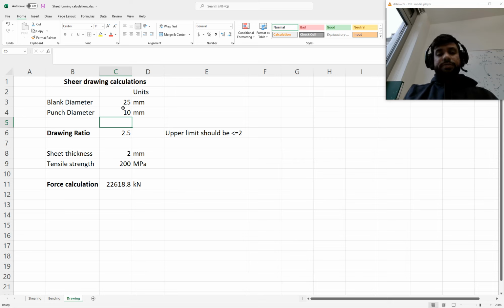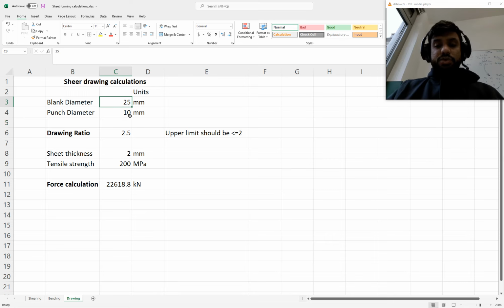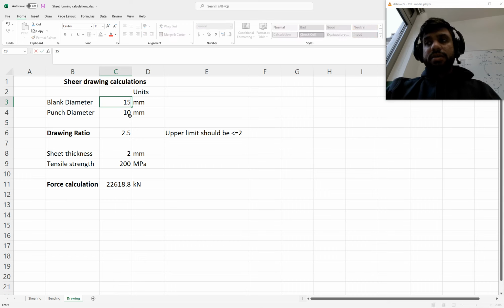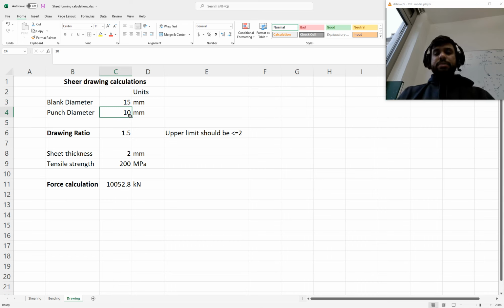So if the draw ratio is 2.5, then it will be difficult to process it using this method, and there are other methods to do it, which is incremental deep drawing and so on, which we are not going into right now. But what we need to do is either increase the punch diameter or decrease the blank diameter so the draw ratio can stay below 2. So I will write here 15, and the punch diameter is 10. Now the draw ratio is 1.5, which is less than 2, so that is okay.